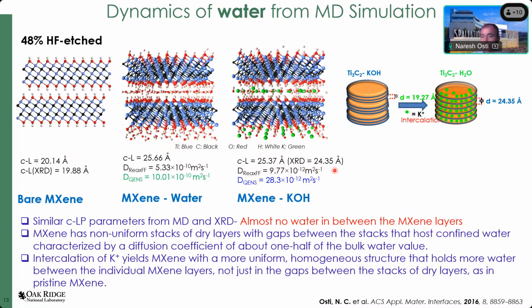Now, before I move to the other example, I'd just like to point out that in this particular study, we have used MXene synthesized using 48% hydrofluoric acid. This is very important because the concentration and the type of the etching agent that you use determines the morphology of this material, giving different information in terms of the diffusivity or the immobilization of the ion in the different types of electrolyte systems that we study. So that's a very important thing to remember.